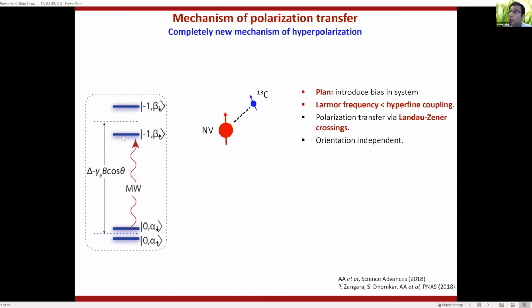So when you work at low magnetic field, this energy gap is only set by the Larmor frequency, or the Zeeman interaction of the nuclear spins. But this energy gap is set by hyperfine couplings that can be larger. And because of this difference in energy gap, you can set up a bias in the system. How I like to think about hyperpolarization is that you have to introduce bias in the system. So you start with spins which are unpolarized, which means that these two spin states are equally populated. So also these two spin states are equally populated.